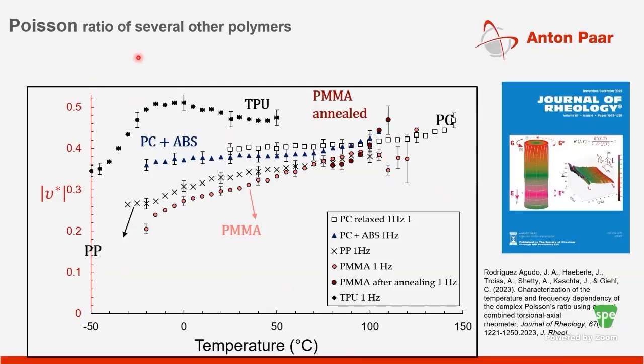Having a combined axial-torsional device really opens up new experimentation for folks, and this could have significant implications, especially for people working in simulation groups doing FEM or finite element type simulations and modeling. Most times they need data on Poisson ratio to model systems, and typically there is no data, or it's very scarce. So measuring it really helps in that case.